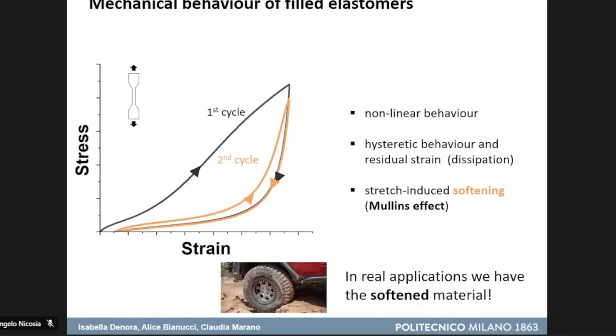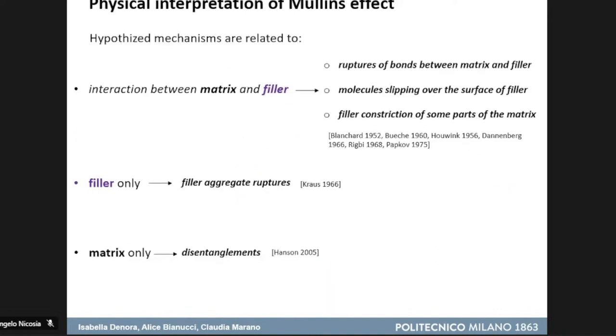It's important because in real applications we have objects that are subjected to different loadings, so we have to consider the mechanical behavior of the softened material. There are different interpretations present in literature about the Mullins effect. We have some hypotheses that concern mechanisms related to the interaction of matrix and filler, or just the filler, or just the matrix. And in order to explain what this Mullins effect is, some experimental works have been performed in literature, especially in uniaxial tensile conditions.